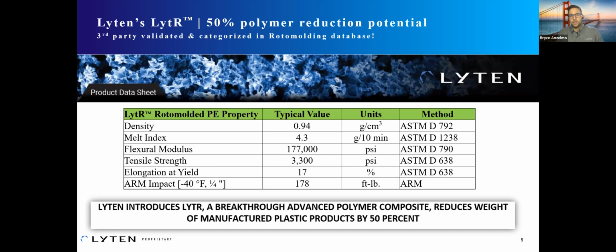What we've been tasked with a lot here, and that the industry needs, is really a stiffer polymer system. So what we've developed and engineered for is a flex modulus improvement, really as the driver for stiffness, or criteria for stiffness as a screening mechanism. You'll see here the flex modulus in the middle, 177 KSI, based on the ASTM standard, is about a 40 to 50% improvement on stiffness over the base polymer system. Again, in application, rotomolded. For those that aren't familiar with rotomolding, you have a melt polymer that's in an oven that's rotationally molded, and then that product comes out. I'll show a couple pictures here on the next slide and one of the partners that we're working with on that to underscore that point.